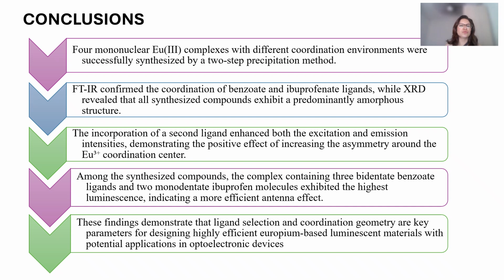As a conclusion, 4 mononuclear europium complexes with different ligand environments were successfully synthesized. Also, FTIR confirmed the coordination of benzoate and ibuprofen ligands, while X-ray diffraction revealed that all synthesized compounds are predominantly amorphous.